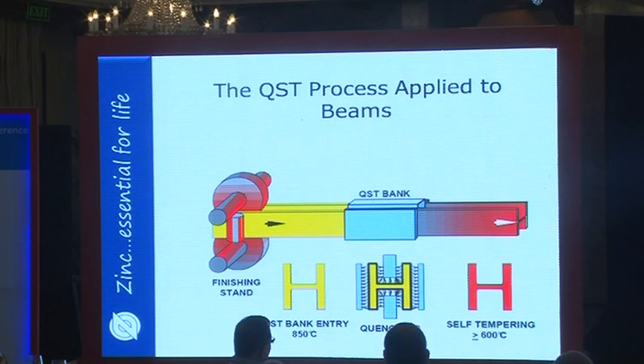This process is now used in North America. It's being used in Europe a little bit, but you are going to begin to see these QST types of beams coming in for hot dip galvanizing. This process is growing. There's more lines that are using these, and so these are leaner steels. We'll have to understand how the galvanizing process affects the mechanical properties of these, because actually galvanizing is even more of an imposed tempering that'll be put on there at 460 degrees, of course, with the zinc dipping. This is all news to come.